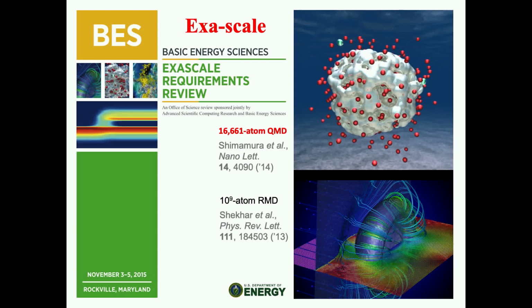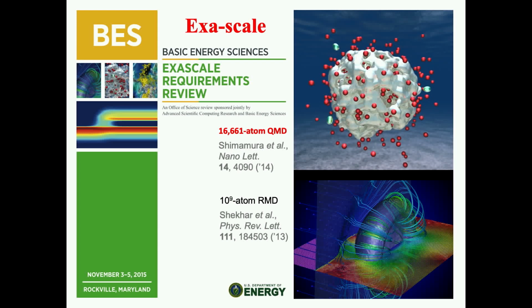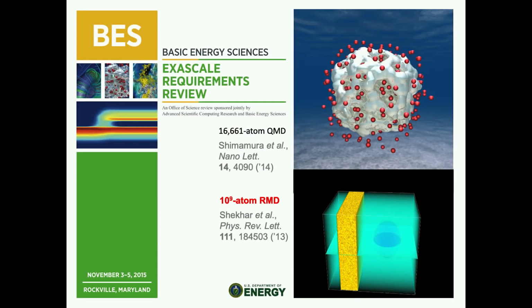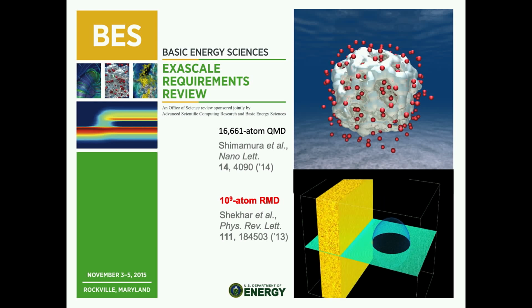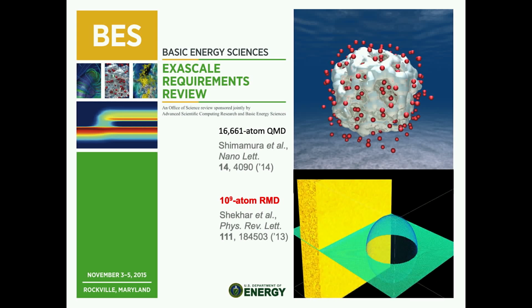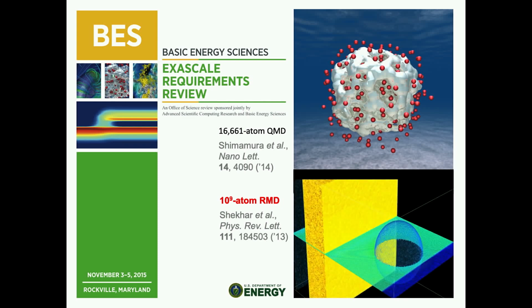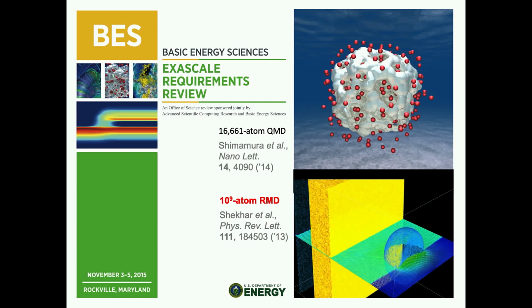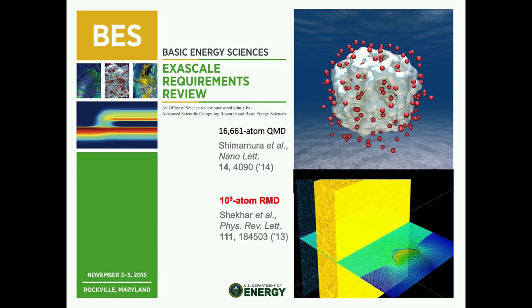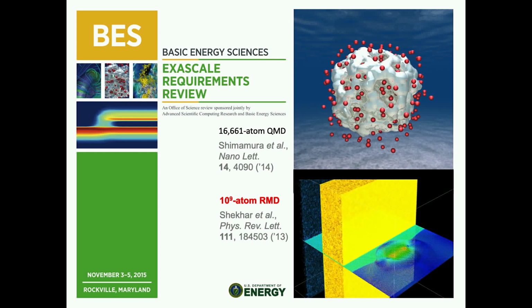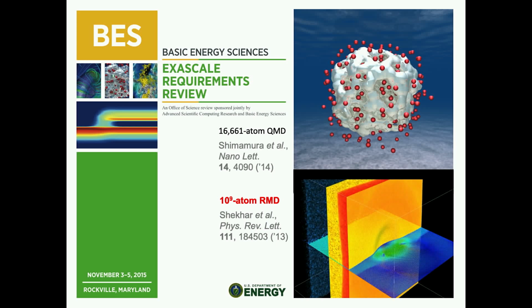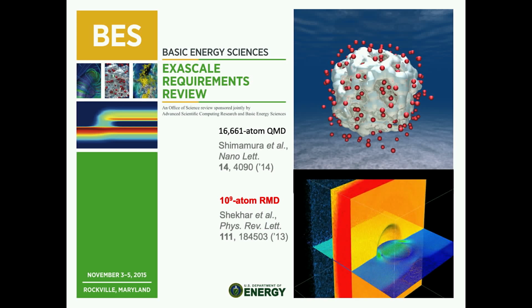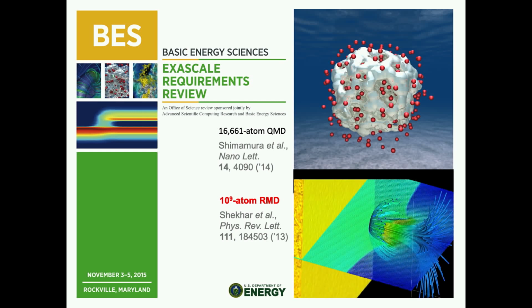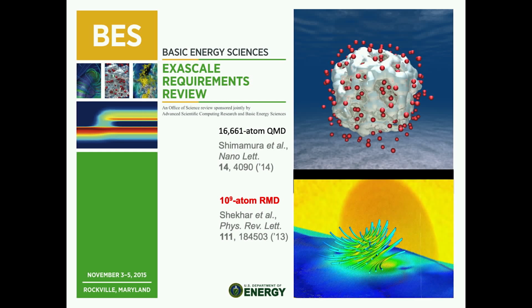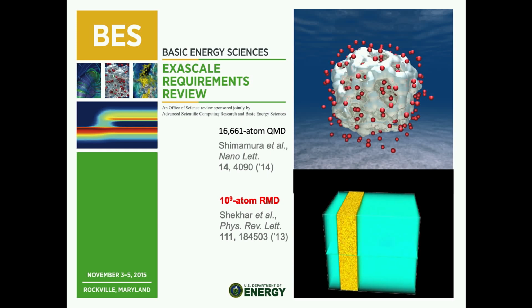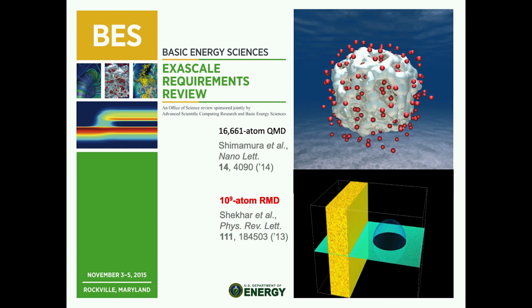Another image here was a billion atom reactive molecular dynamics simulation. What we study is the so-called cavitation bubble collapse in water near a solid surface, in this case a silicon dioxide surface. And actually, we are sending a shock wave to quickly collapse this cavitation bubble. And this collapse of the bubble creates a shock wave. So this is a shock wave. And these shock waves hit the silica surface to damage it not only mechanically, but also chemically. That's the power of reactive molecular dynamics. And here, this nanojet is formed, which is represented by a streamline. So the bottom line is that with a billion atoms, you can do fluid dynamics atom by atom. So that's the message.